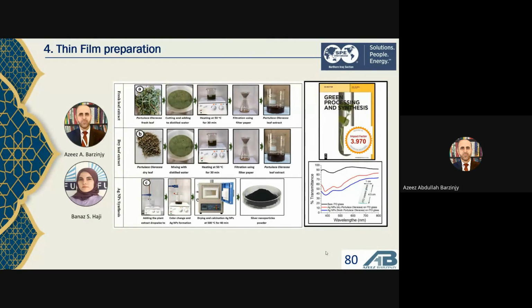So as you can see, UV is the highest energy from the solar spectrum. The black line here represents the bare indium tin oxide glass, and the red one is the Ag nanoparticle produced from dry plant extract, and the blue one, which is the best one, is Ag nanoparticle from fresh plant extract. And this project is very important because you can see that the amount of the absorption reduced from about 90% to only 40% or even less.